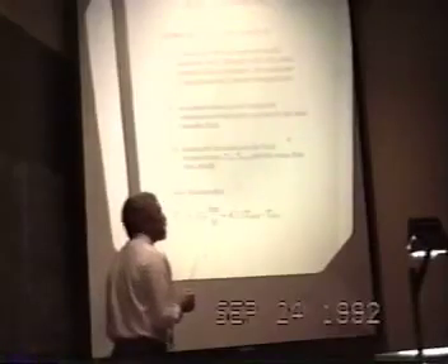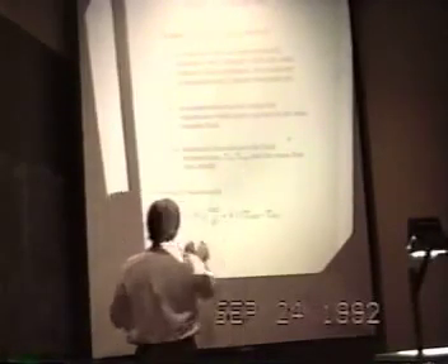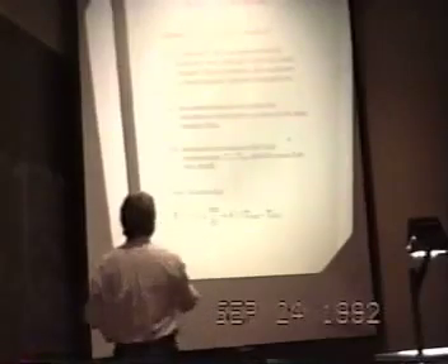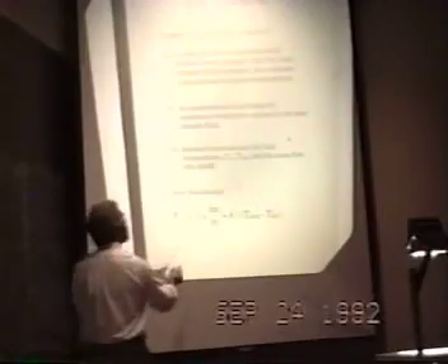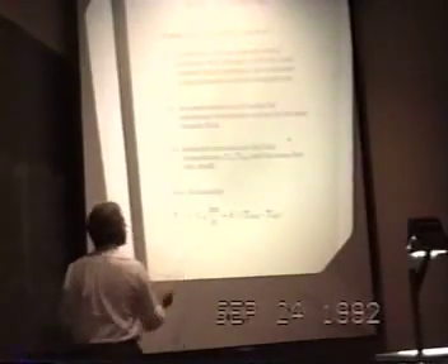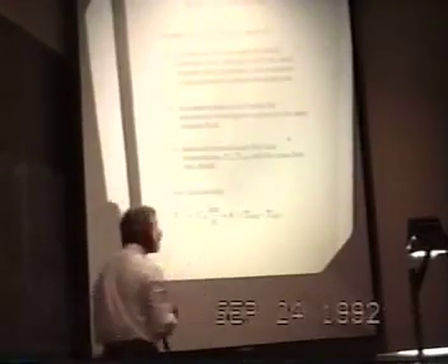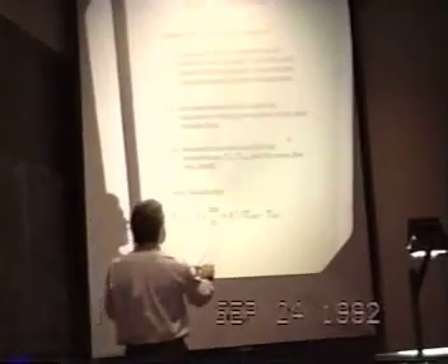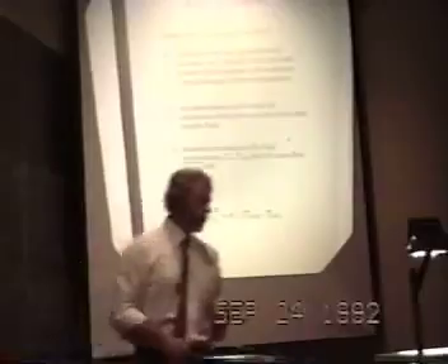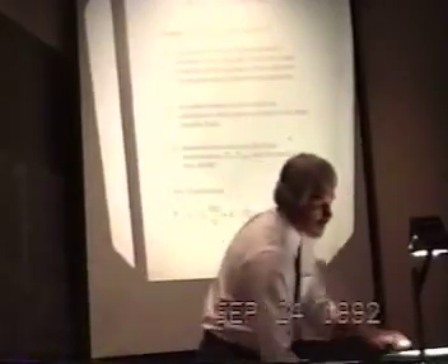So the sensitive parameters, the parameters which might be subject to systematic errors, are the inlet temperature, the outlet temperature, and the mass flow rate, so that the power measured by such a calorimeter depends on the heat capacity of the fluid, the mass flow rate, a conductive loss term as that fluid loses heat to its environment, and the inlet and outlet temperatures. This is the only equation which governs the steady state operation of this calorimeter.